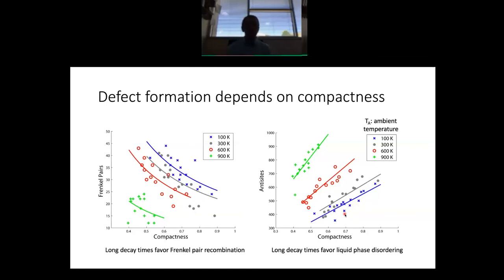Well, it turns out that when you plot the number of Frenkel pairs versus the compactness, and you can also plot the number of anti-sites versus the compactness, you see opposite trends. The more compact a thermal spike is, the fewer Frenkel pairs it has. The more compact the thermal spike is, the more anti-sites it has. And this is really easy to explain based on the decay time argument. Right? So if the decay time for a high compactness thermal spike is large, that means that any Frenkel pairs that were generated have more time to recombine. So the higher the compactness, the more Frenkel pairs recombine, the fewer are left over. On the other hand, the longer the decay time, the more time the nickel-3 aluminum has to disorder in the liquid phase. So the higher the compactness, the longer the decay time, the more time there is to disorder. So that means you get more anti-sites, right? So you get these sort of interesting opposite trends in the defect formation with respect to the shape of the thermal spike. That's it.